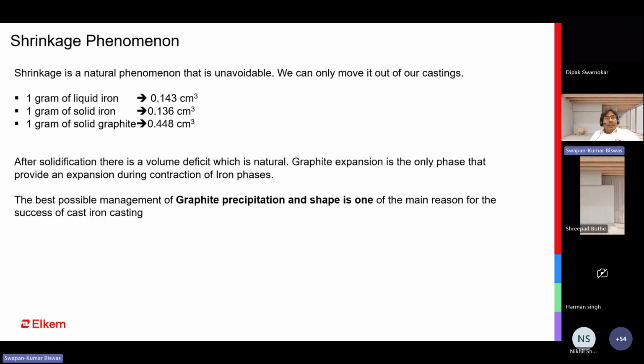So we can improve this graphite precipitation by taking corrective action in the base metal. See, any metal when it is inside this furnace, you can take corrective action. But after tapping from this furnace to the ladle, maybe in case of gray iron the pouring ladle, or in case of ductile iron the treatment ladle, then you don't have much time to take any corrective actions.